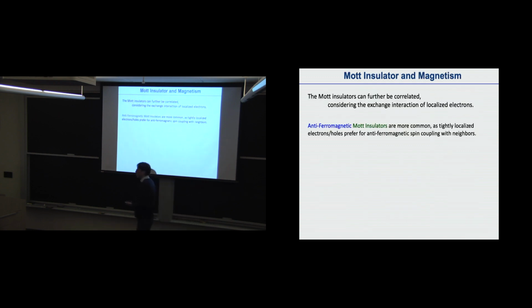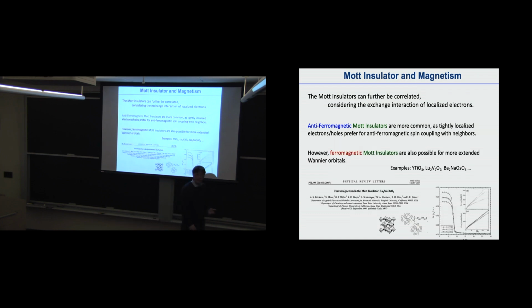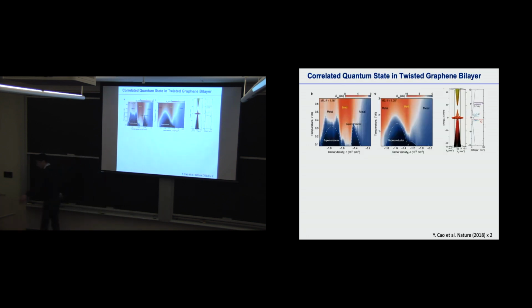But nevertheless, Mott physics itself does not completely dictate what magnetism is expected. In fact, if you make the residual interactions between electrons in the Mott lattice relatively long range, one can actually make a ferromagnetic Mott insulator. Indeed, experimentally, it has been seen that ferromagnetic Mott insulators do exist—here are some examples, done by Ian Fisher's group recently. There are a few examples, not as common as antiferromagnets, but ferromagnetic Mott insulators do exist. Now, coming back to the Mott insulator realized in graphene by Pablo's group.